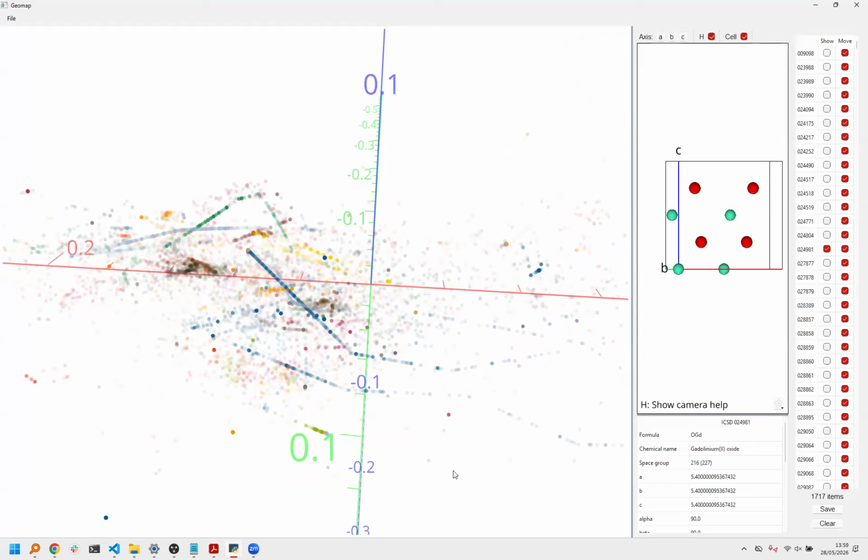So say extending one side of a unit cell, just stretching the unit cell in one direction, anisotropic scaling, or possibly an atom which can be located at, say, I'll show the example in a sec. Maybe its coordinates can be something like 1/4, 1/4, 1/4 plus epsilon, where epsilon can range from 0 to 1/4, and that one parameter is all that's really distinguishing, it is changing in this sort of family of crystals, well, that results in a very consistent movement along this space because we have continuity.